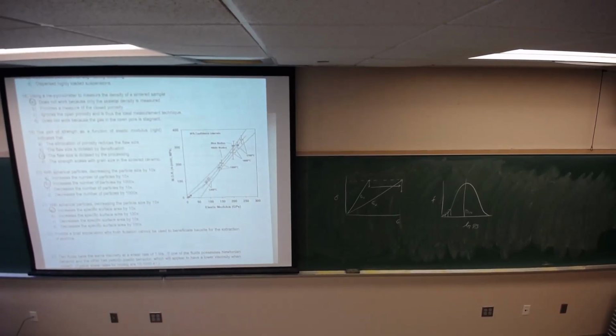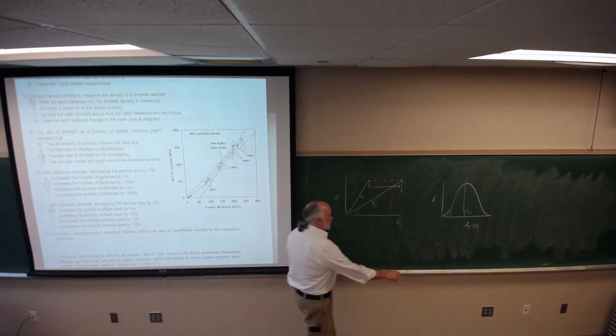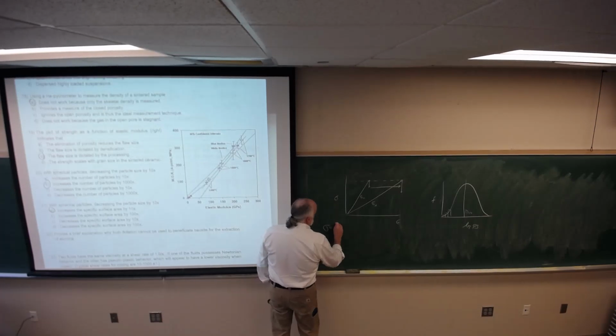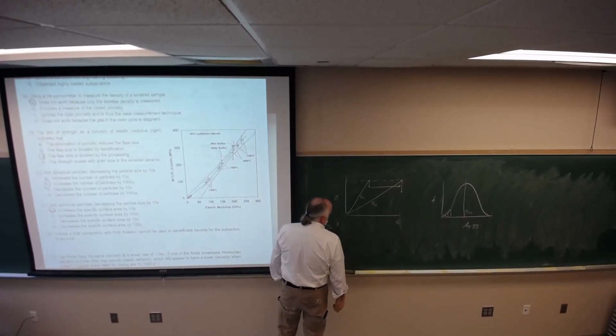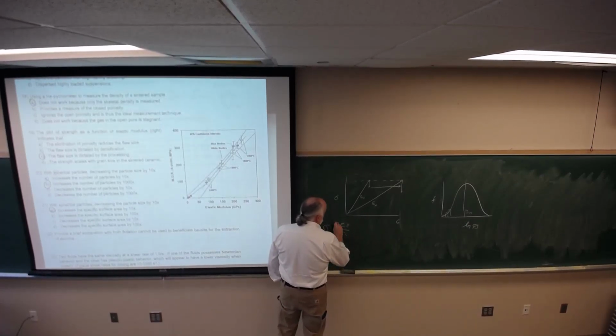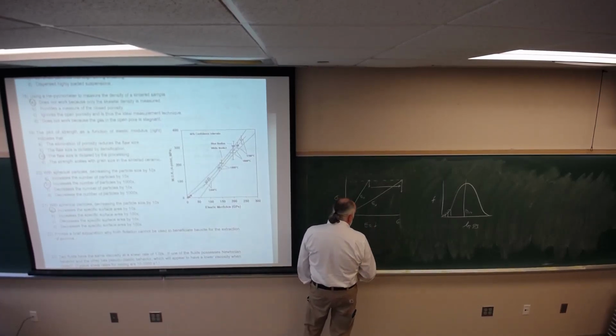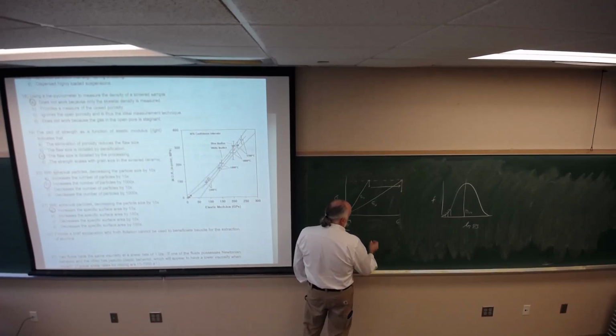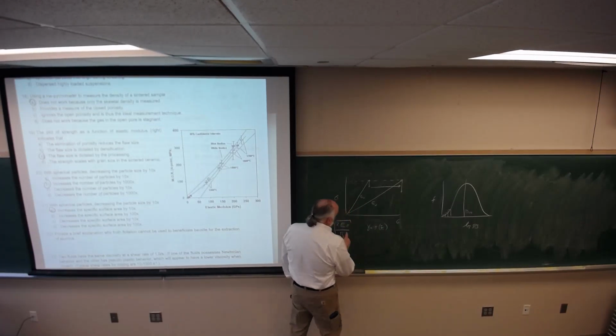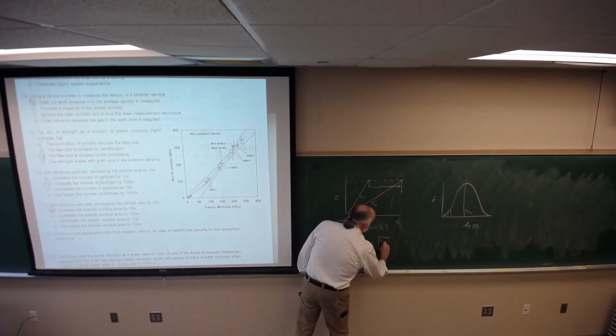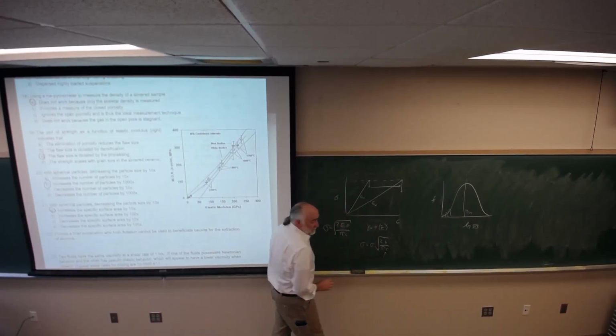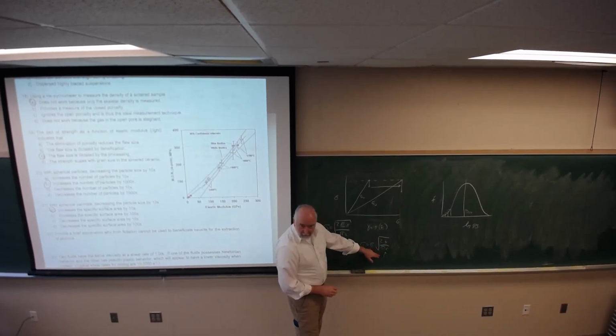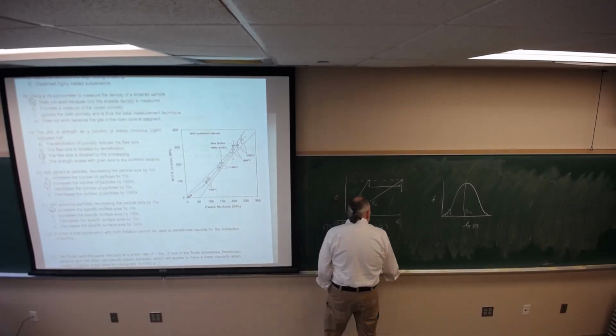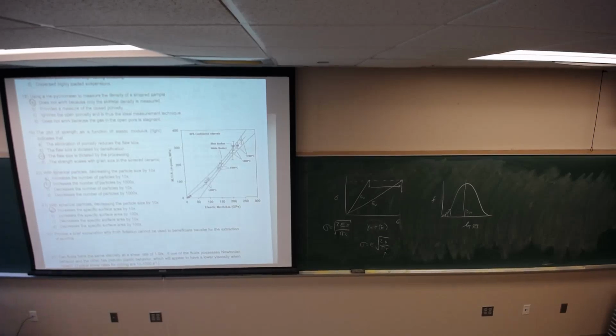Okay, 19, plot of strength as a function of elastic modulus indicates that the flaw size is dictated by the process. Because what you're seeing is that the strength scales linearly with elastic modulus. And when that is the case, we have a relationship that gamma is a function of E. So this becomes sigma equals E times the square root of 2 gamma over pi C, where C is your critical flaw size. So if this scales linearly, the slope of this line is your strain at failure, but it also indicates the flaw population. And that indicates that the flaws are constant. That means they're dictated by the process.